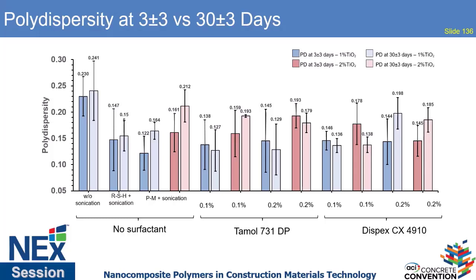You can see on some of the graphs that we have a slight reduction or slight increase in the polydispersity, and this is when you're running the samples. If you have agglomerates in the sample, even though they're properly dispersed, sometimes when you're testing, you might grab something slightly larger than the others, which could lead to some of the results we are seeing here.